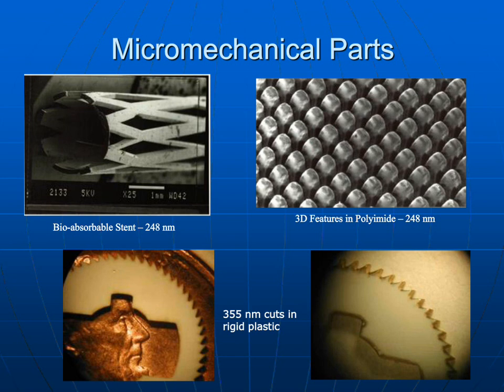On the top right, you'll see 3D features in polyimide. Those streets are about 10 microns wide, and the bumps are on the order of about 30 microns. So we made these extremely small features in a piece of polyimide. On the bottom, you'll see a gear that was cut out of a piece of plastic, shown with respect to a Lincoln penny. And this gear was taken right off the laser, so it's fairly clean right off the laser.